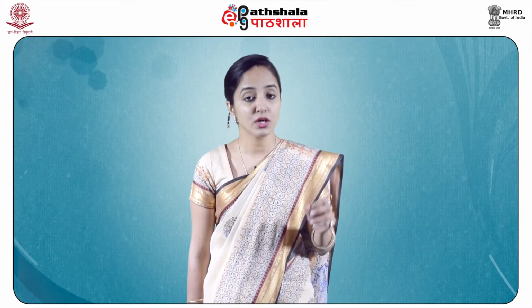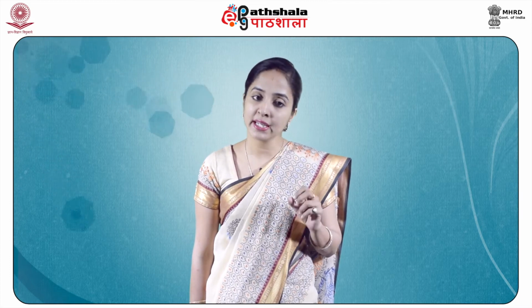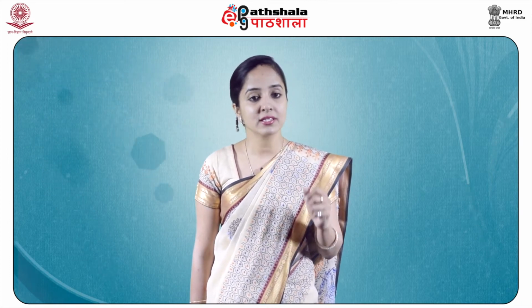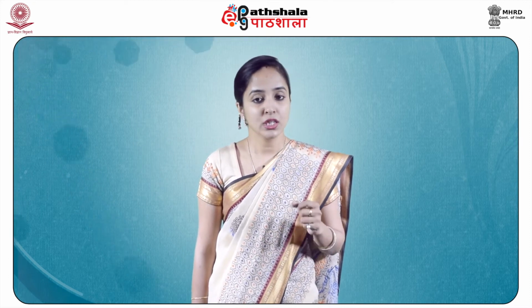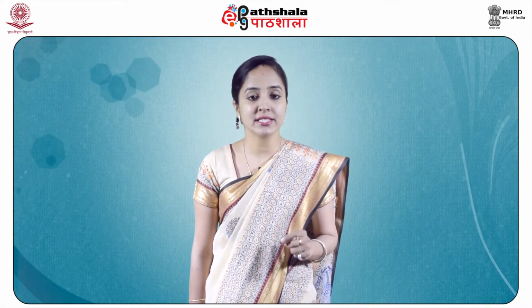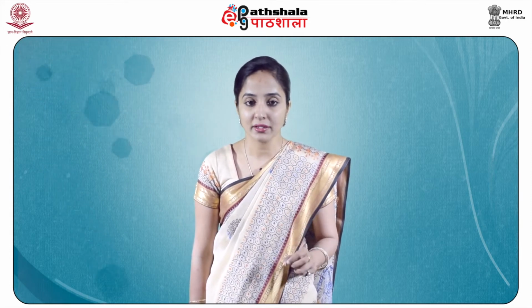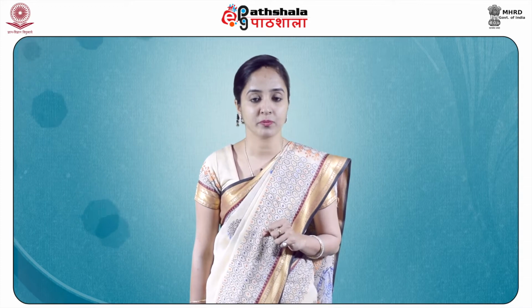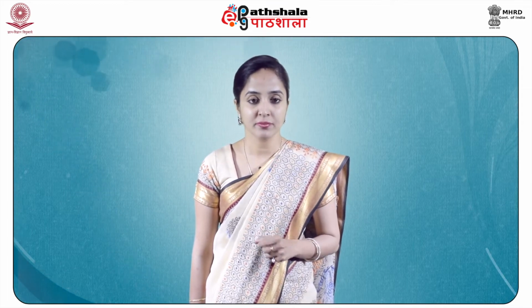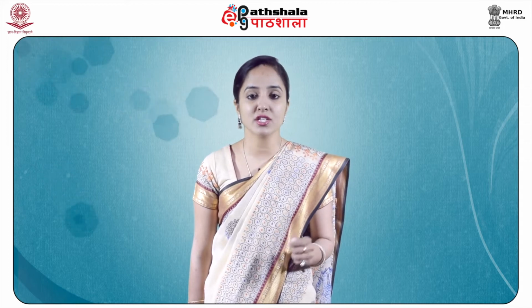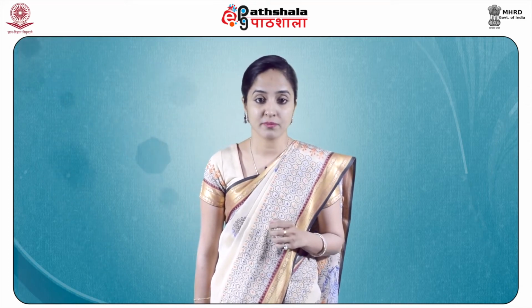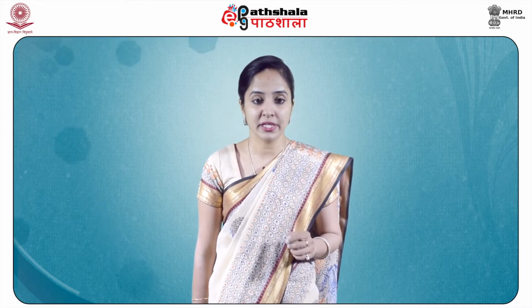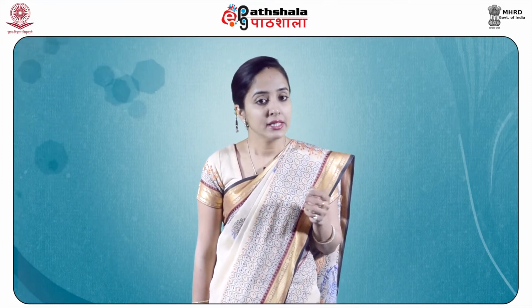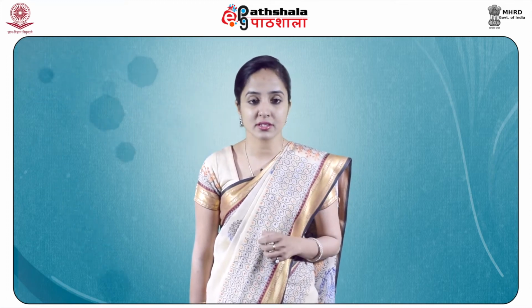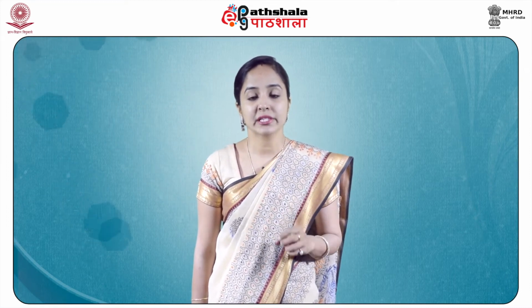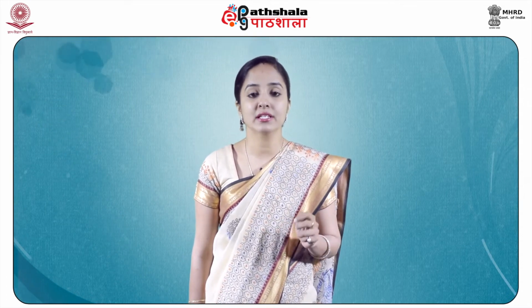Neutron activation analysis, or NAA as it is called, is a sensitive analytical technique used for qualitative and quantitative multi-element analysis of major, minor and trace elements in the samples. Neutron activation analysis offers sensitivities that are far superior to those attained by other methods, on the order of parts per billion or even better. The application of neutron activation analysis is so widespread that approximately 1 lakh samples undergo analysis each year.